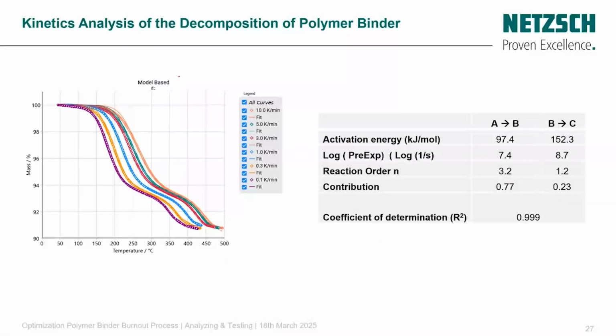Also, we can get the different kinetics parameters: the activation energy for each single step, the log of the pre-exponential factor, the reaction order, and the contribution. And the contribution here is the quantitative contribution of each step to the overall process. And here you can clearly see that the first step is around 0.77, and the second one is 0.23, the contribution of each single step.